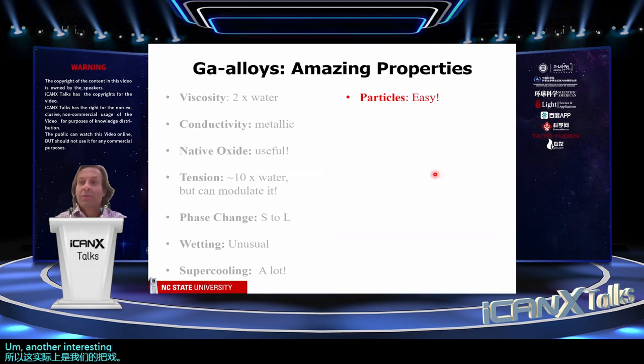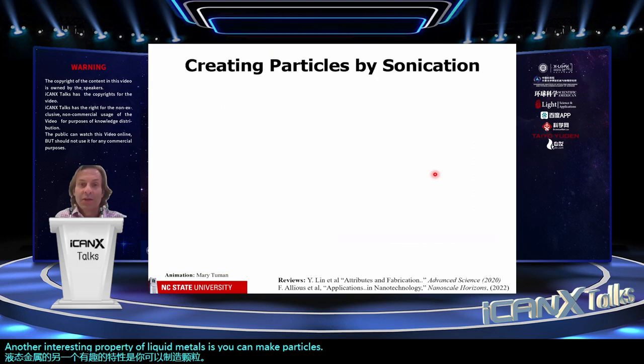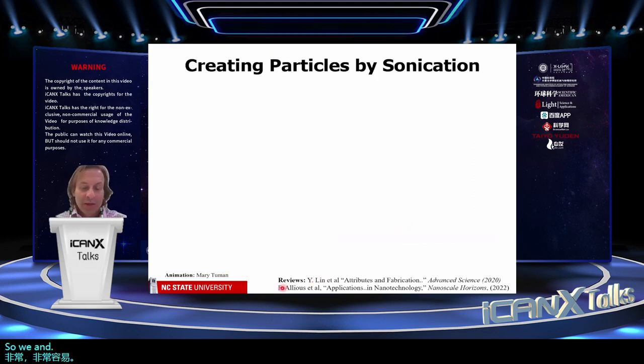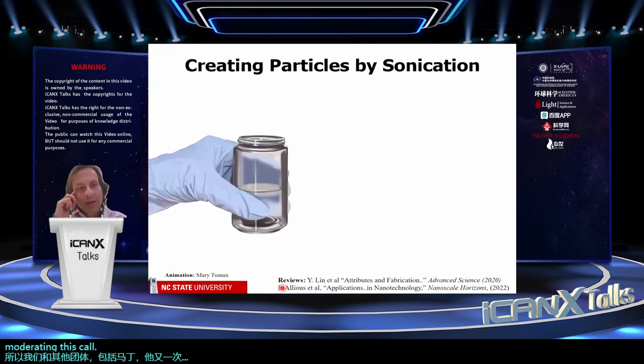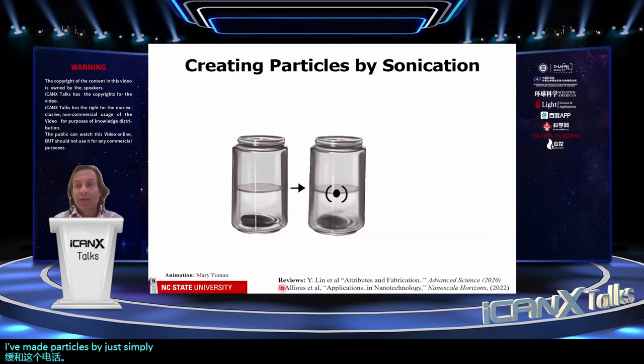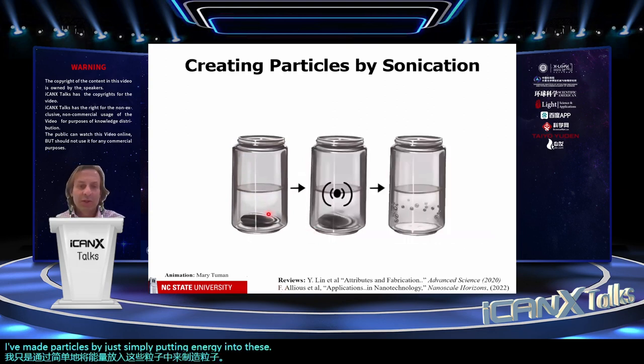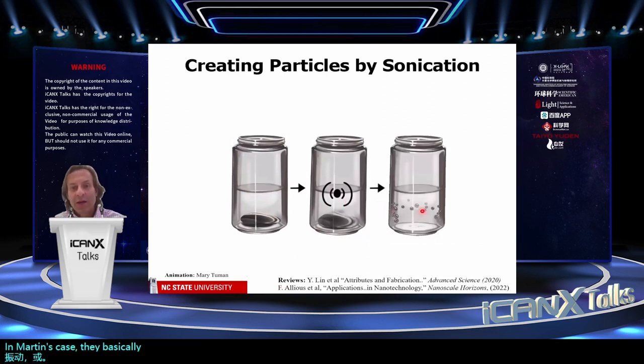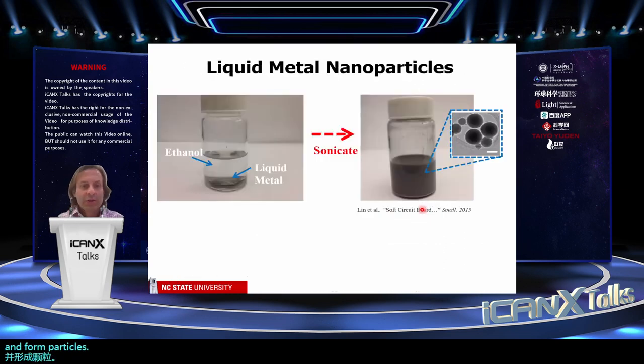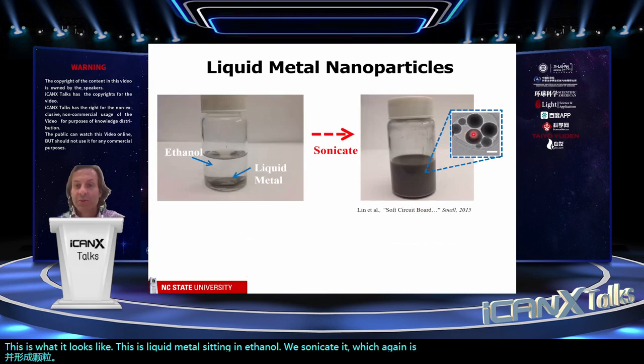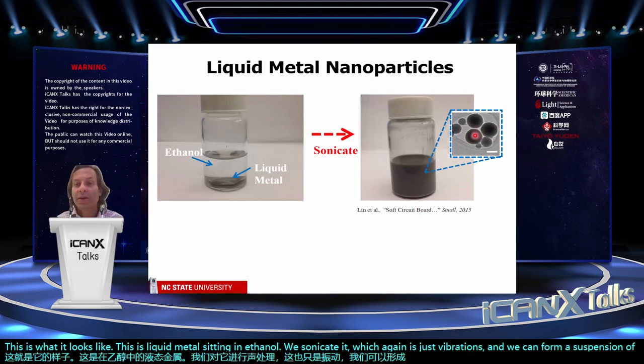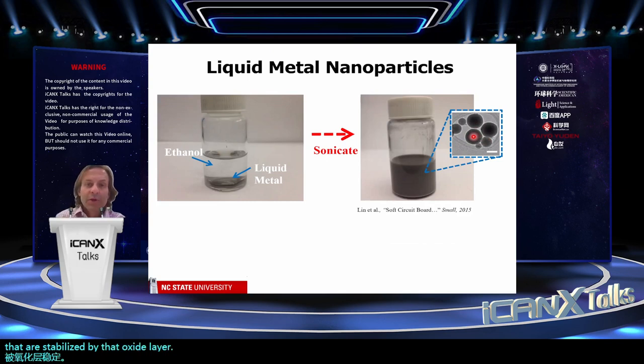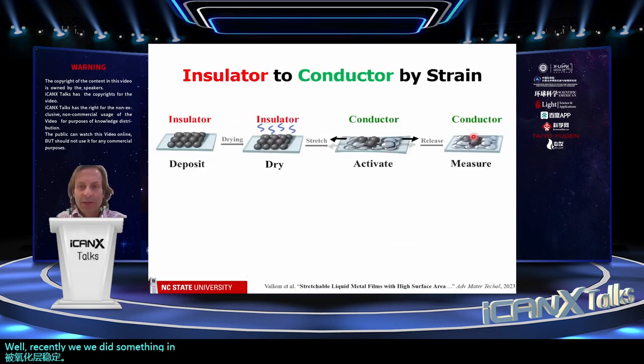Another interesting property of liquid metals is you can make particles very, very easily. We and other groups, including Martin, who's moderating this call, have made particles by simply putting energy into the liquid metal. Here we take a vial of liquid metal and vibrate it, or in Martin's case, they stir it, and form particles. This is liquid metal sitting in ethanol. We sonicate it, which again is just vibrations, and we can form a suspension of little particles stabilized by that oxide layer.